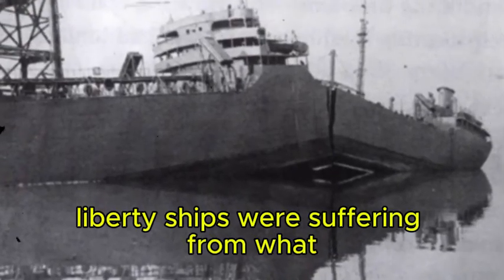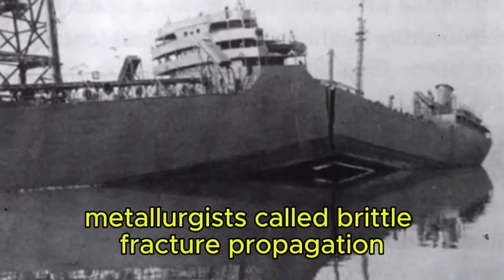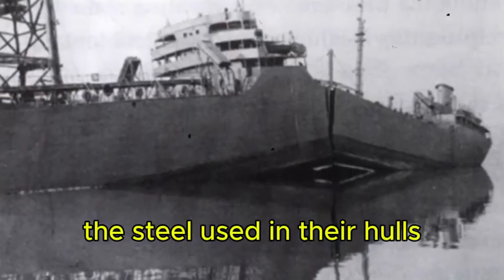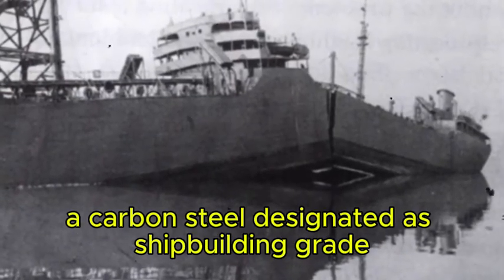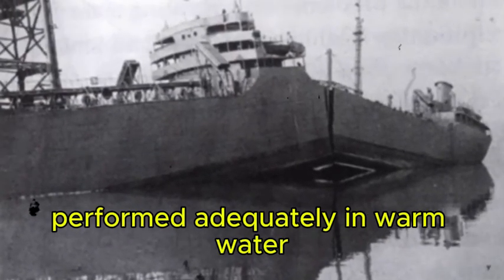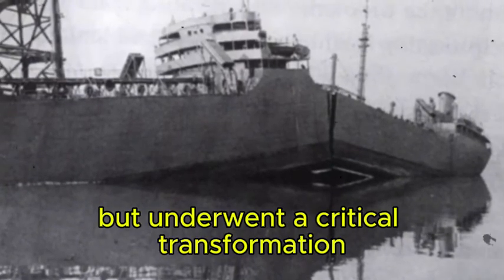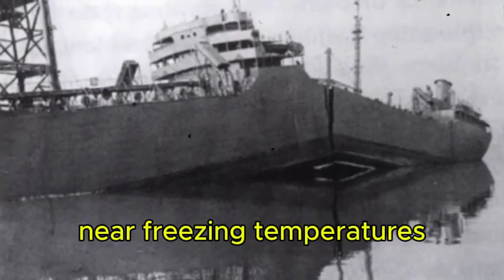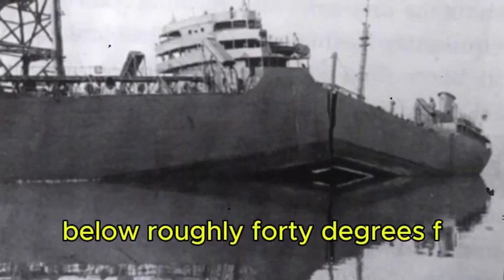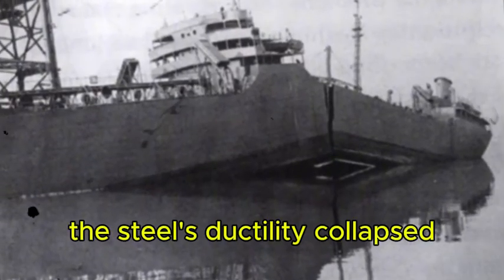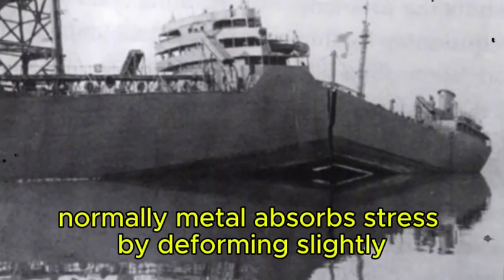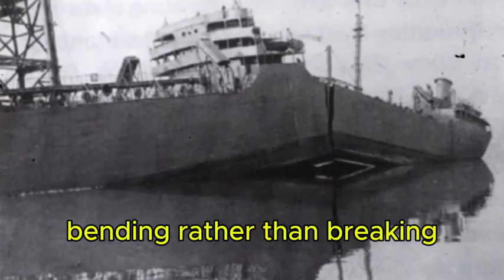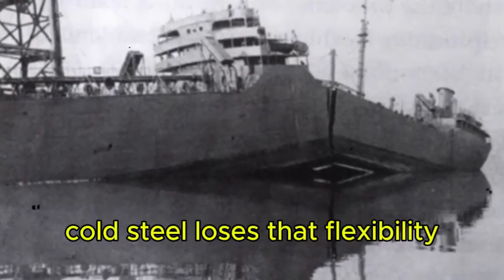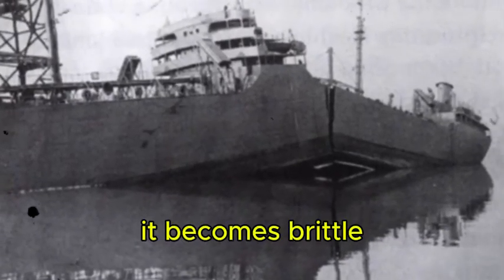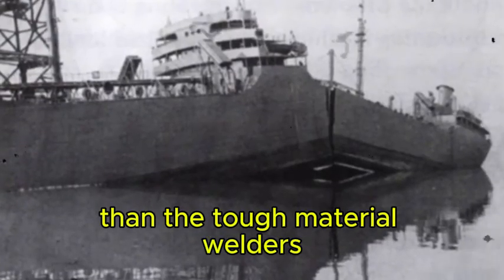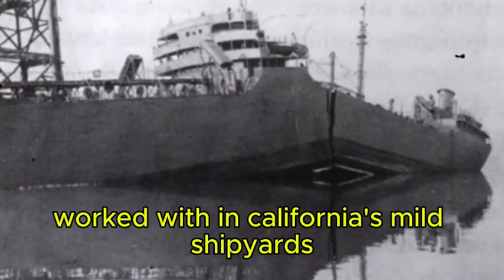Liberty ships were suffering from what metallurgists call brittle fracture propagation. The steel used in their hulls, a carbon steel designated as shipbuilding grade, performed adequately in warm water, but underwent a critical transformation in the North Atlantic's near freezing temperatures. Below roughly 40 degrees F, the steel's ductility collapsed. Normally, metal absorbs stress by deforming slightly, bending rather than breaking. Cold steel loses that flexibility. It becomes brittle, more like glass than the tough material welders worked with in California's mild shipyards.